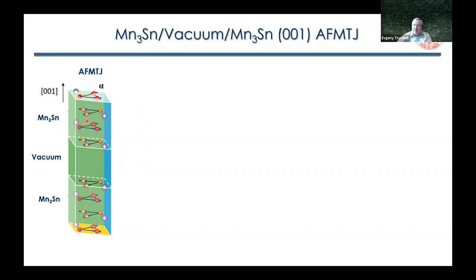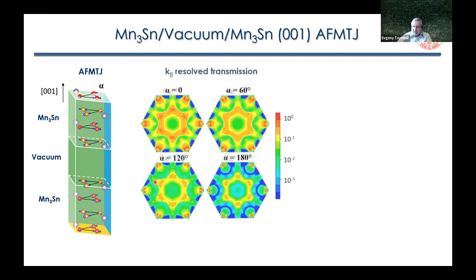This is the geometry of the tunnel junction. What we do here is fix the orientation of the magnetic moments in the bottom electrode, then rotate the Néel vector of the top electrode by an angle alpha with respect to the bottom electrode, and calculate the transmission. This is what is shown here. At angle equal to zero, we have a quite complex distribution of the transmission, with red being high transmission. Now as the mismatch between the Néel vectors increases, we go from high transmission to lower, and eventually, from the contrast, you see that the transmission is substantially reduced.